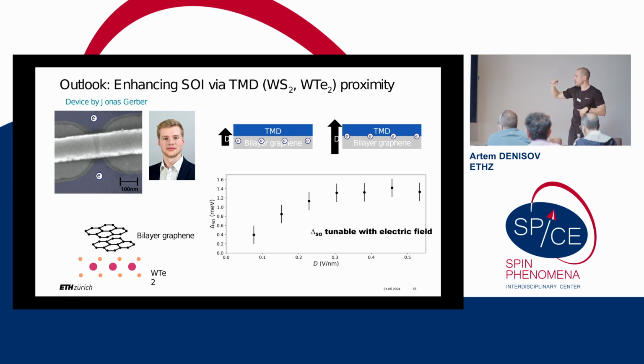And Jonas recently got very nice results where, indeed, by putting a TMD on your bilayer sheet, you can increase your spin-orbit coupling more than 10 times, as shown here. But most importantly, as we move our carriers away from the TMD by this displacement field, we can tune the spin-orbit coupling, reducing it back to its intrinsic value. And opposite, as we move carriers closer to the TMD, we can see how spin-orbit coupling is increasing.